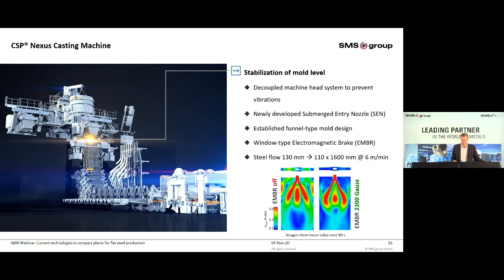In the design phase, several CFD simulations were done at SMS. The figure at the bottom shows the result of a simulation with and without the EMBR at a high steel mass flow. The crucial factor is the steel velocity at the mold level. A too high velocity will end up in unstable casting conditions due to uneven melting of the casting powder and an inhomogeneous heat transfer in the mold.